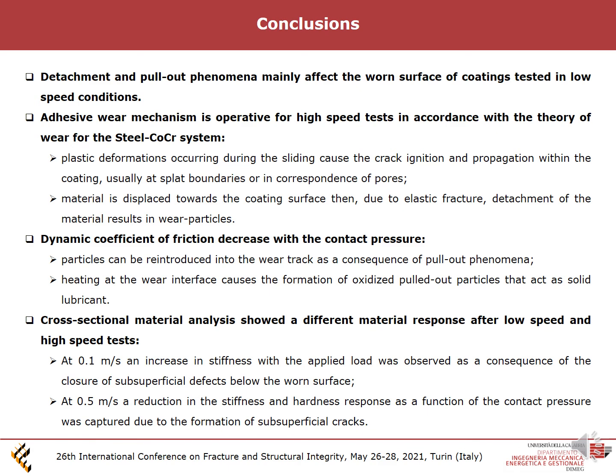Regarding the evolution of the dynamic coefficient of friction, the latter tends to decrease with the contact pressure because particles can be reintroduced into the wear track as a consequence of pull-out phenomena, and the heating produced during the sliding causes the formation of oxidized pulled-out particles that act as solid lubricant.